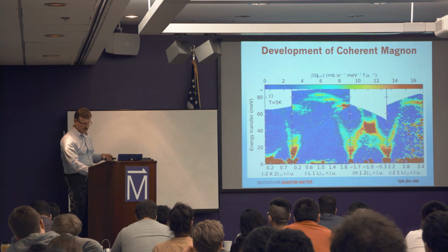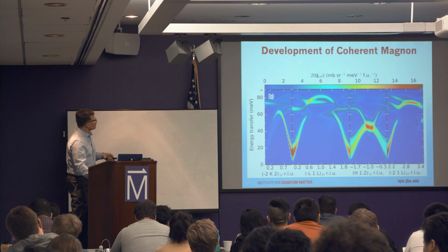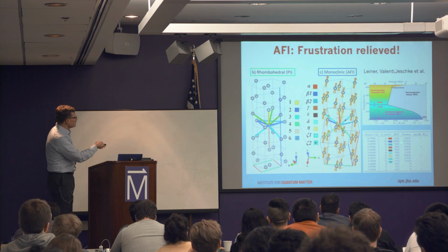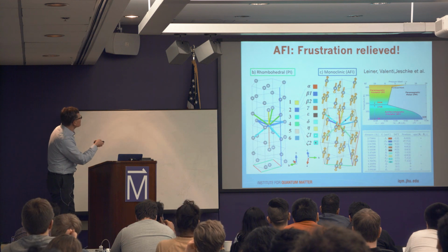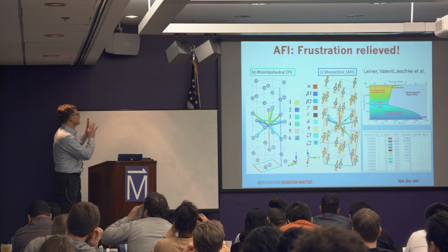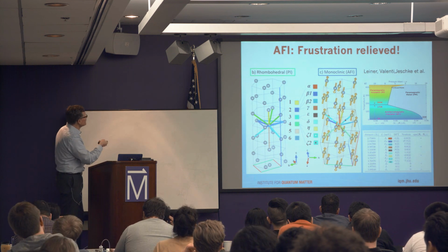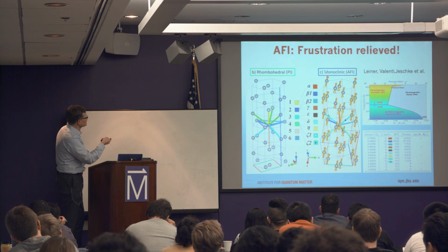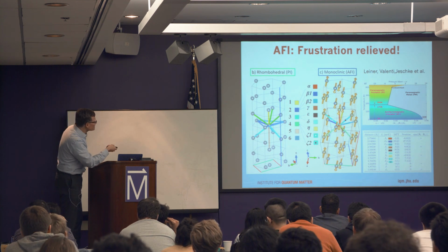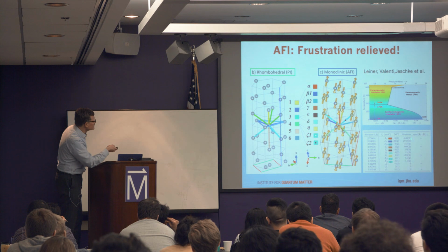So it's a very complicated compound, a lot of exchange constants, and we end up being able to extract a table of exchange constants here. So this is the paramagnetic insulating state where we have to rely entirely on DFT to obtain the exchange. This is the monoclinic state. This is the ordered structure. And then here you have all of the different exchange constants that we determined from DFT and then through the